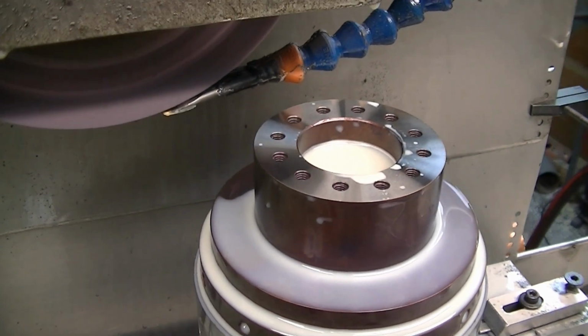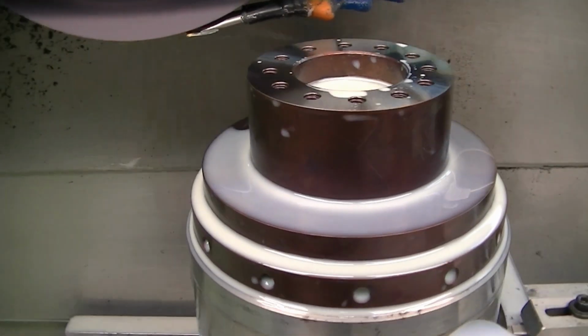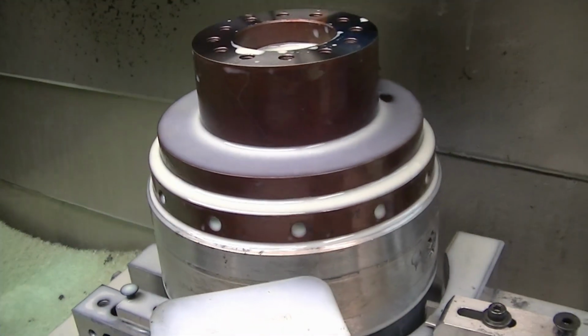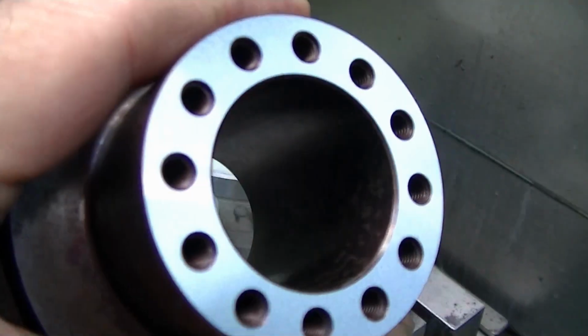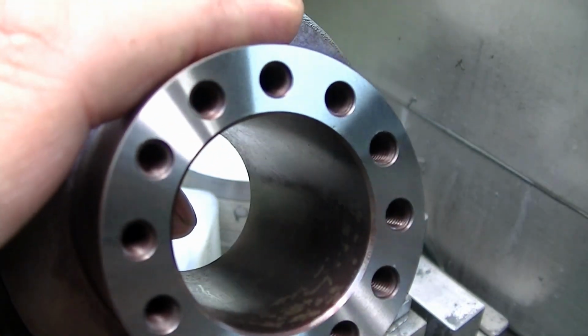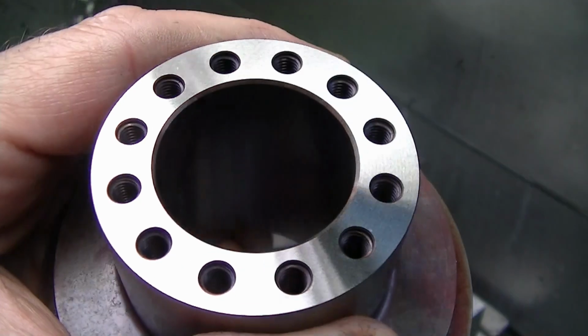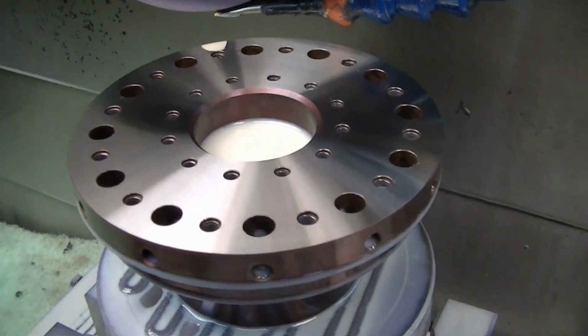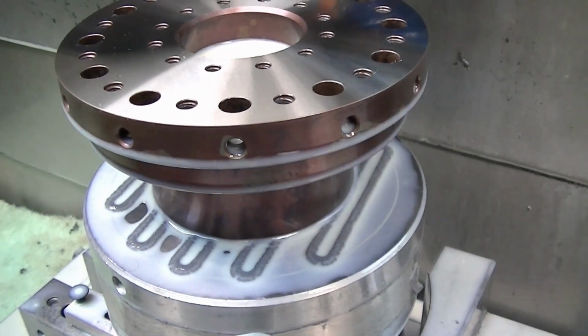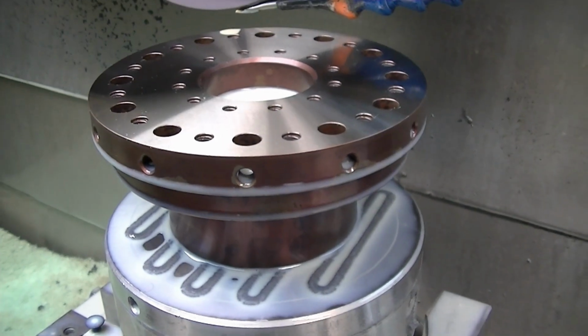Generally, when doing parts like this with a larger face and a smaller face, it pays to reference off the large face and grind the smaller. This will generally give you less material removal required to get parallelism. There's the larger face ground parallel to the smaller face we did earlier.